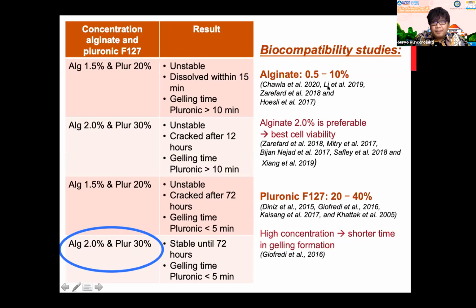And about the biocompatibility study, actually alginate from 0.5 until 10% is acceptable. But in our study, we chose alginate 2% because it is preferable, as it can provide the best cell viability. And also about the pluronic F127 that we use, actually we can use concentrations ranging from 20 until 40%. And if we use a high concentration, it will have the consequence of a shorter gelling time. Actually, this consequence will be beneficial for us as the inventors, because we need the encapsulation to be as short as we can.